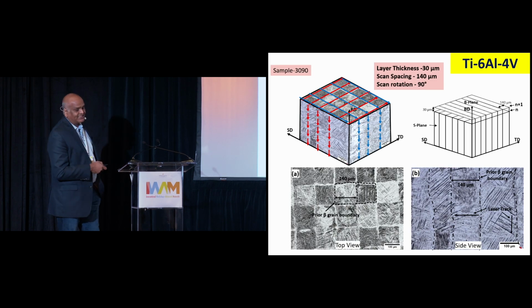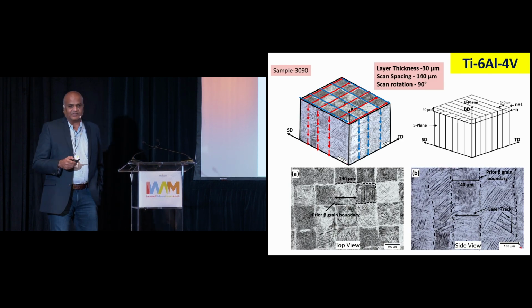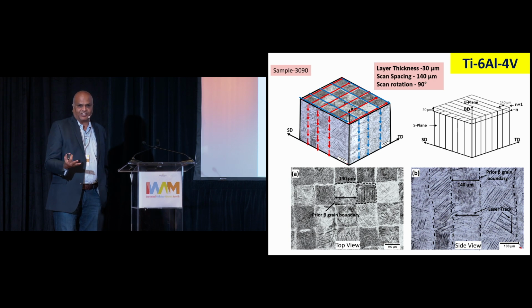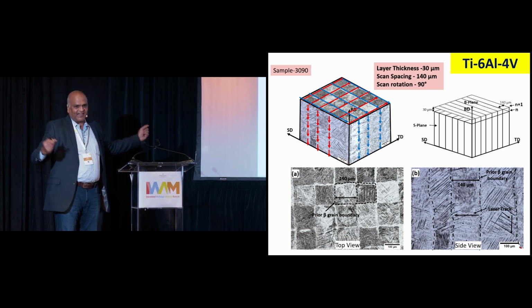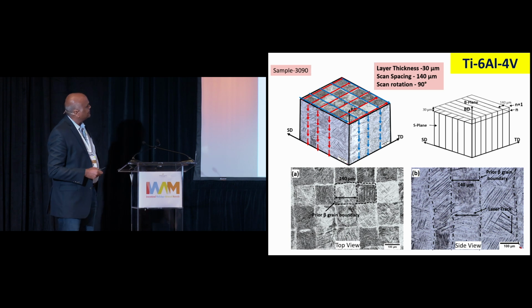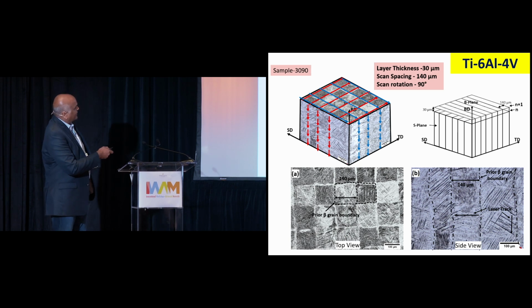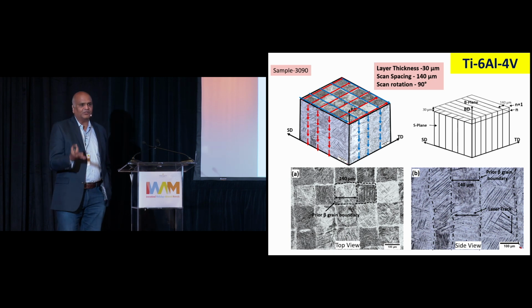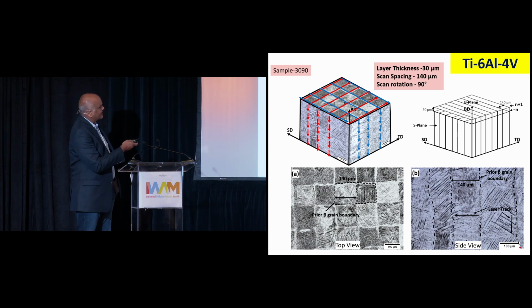Take titanium-6-aluminum-4-vanadium, a very important alloy. In airplanes, the big front blades are made of Ti-6-4. If you use a 30 micron layer thickness and a scan rotation of 90 degrees between layers, you get square grains on the top surface, and on the side these are all columnar. Epitaxial growth actually exists because the layer thickness is smaller.